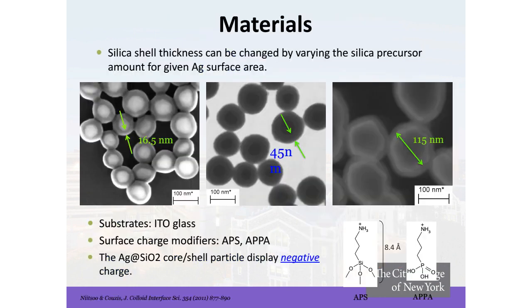This is a picture to show you that the process is actually quite robust, and we've been able to scale these particular core shell manufacturing processes. We can have cores and shells in the range of 16.5 nanometers, all the way up to 115 nanometer total diameter of the particle. And we've learned how to build large enough quantities of these materials so that we can overlay hundreds of layers of these colloidal particles onto a substrate for the purposes of forming macroscopic capacitors, where we can now measure the performance of the device.